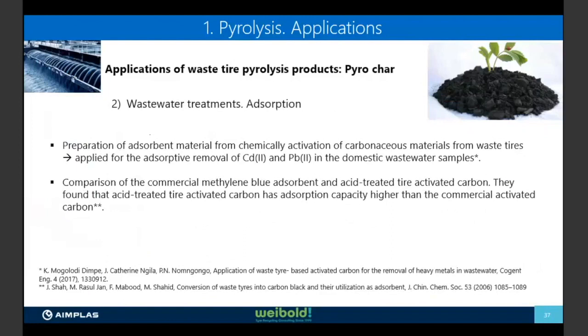Okay, the second application of pyrochar is wastewater treatment. So the preparation of adsorbent material from pyrochar with a post-chemical activation process, okay, is applied to the adsorptive removal of cadmium and lead in domestic water samples. And another study made a comparison of the commercial methylene blue adsorbent and acid treated tire activated carbon, and they found that acid treated tire activated carbon has adsorption capability higher than the commercial activated carbon.